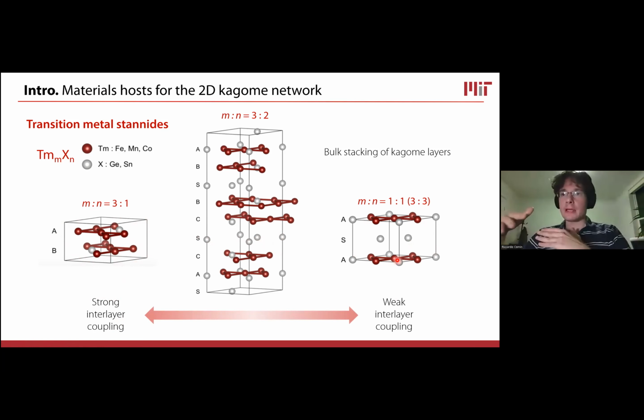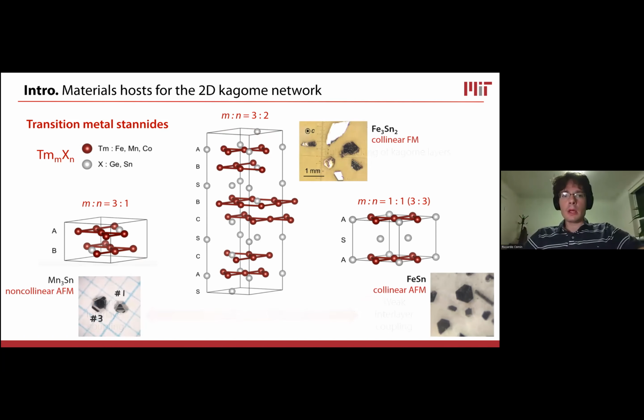And clearly the layer of stannide is not insulating, so it's not an insulating barrier, but still it acts to reduce the interlayer coupling. And we see this kind of effect in the electronic band structure. And then you can construct systems which are intermediate between these two. These are some of the examples of the beautiful crystals that are grown in Joe's lab and that we have had the fortune to study in the past few years.